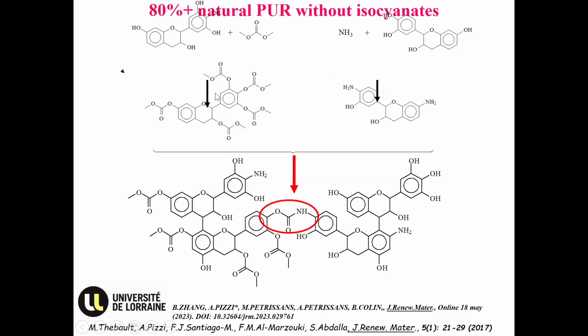Then, as I told you, you can react the carbonated tannin with ammonia. So we introduce the NH2 groups in the tannin. The reaction is quite easy. And then we get a non-isocyanate polyurethane, that's a urethane linkage, between the NH of the aminated tannin and the OHs of the carbonated tannin. And that works very well as well. It doesn't work for adhesive, but it works for coatings very well. There's no problem on that.